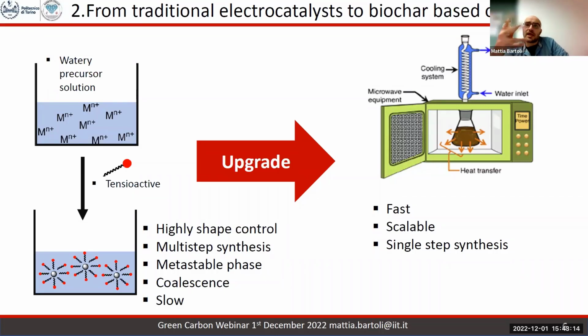We start on the lab scale, of course, so wet approach, small beakers, and a very handy process. But we move from that to something that could also be scaled up. Try to keep in mind that we must produce material with properties that match the requirements for electrocatalysis. One of the approaches that we found quite promising, and a good compromise between lab scale and industrial scale, was the microwave approach.